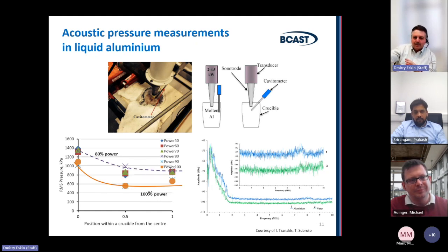When we talk about these acoustic measurements, we are listening to the overall noise, which is created by everything which is happening in the melt: bubbles being created, bubbles imploding, bubbles vibrating. They all emit different signatures. So what we do in this case, we listen to this white noise. Then we process this signal into the frequency domain, so amplitude versus frequency. And then there is usually the fundamental frequency of your main signal.